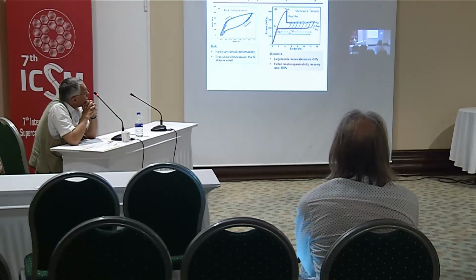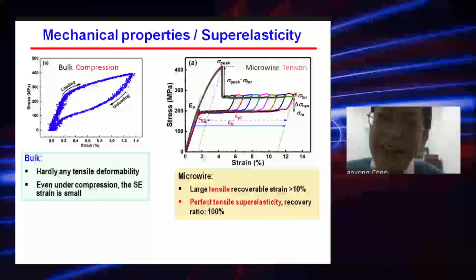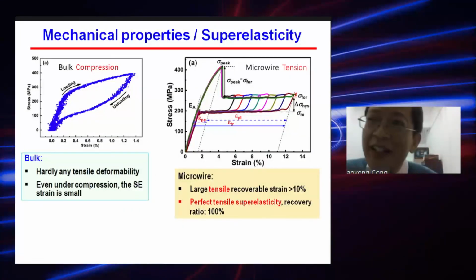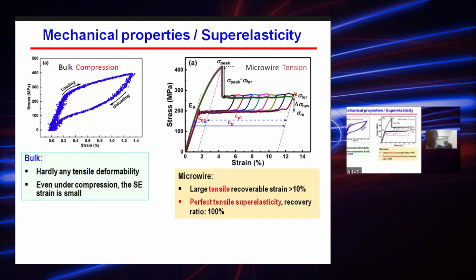Yes, maybe it's possible, because you see in the nickel-titanium wires, in the nickel-rich samples, you can introduce very fine precipitates, Ni4Ti3. Maybe in this kind of material, we can also try to introduce some precipitates. Then we can reduce the barrier for nucleation of martensite without sacrificing the mechanical properties. I hope so. Thank you.